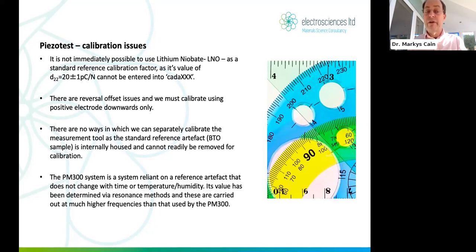Reversal offset issues. It's very important to always have the positive electrode, in other words, the positive charge output electrode, when you apply stress, it must be down, okay? And that's because the top electrode is either earthed, or it's into a virtual earth, and that means you would typically experience offsets, which you don't want to experience in this case.